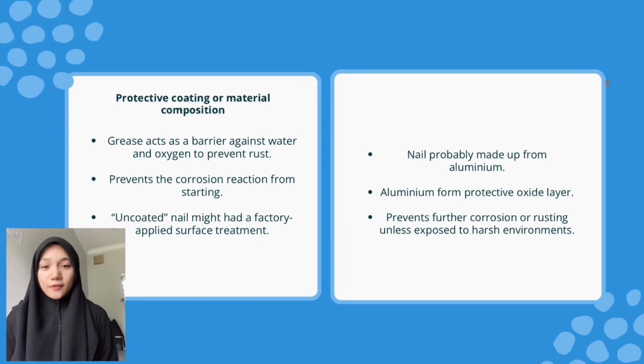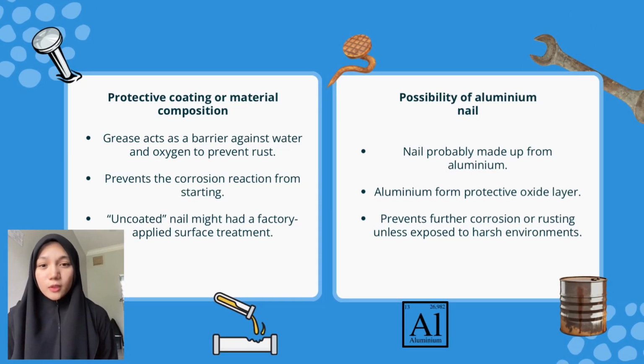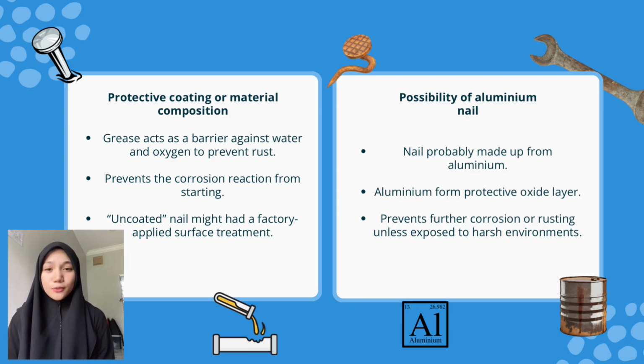The result demonstrates that when we compare with uncoated materials, the application of a protective coating such as grease particularly slows down the corrosion process. Moreover, environmental factors like humidity, sunlight exposure, and air circulation also have an important impact on how quickly the corrosion forms. Overall, this experiment highlights the value of surface treatments in corrosion management and shows that environmental factors alone may not be enough to cause corrosion quickly without exposure to more extreme environments.